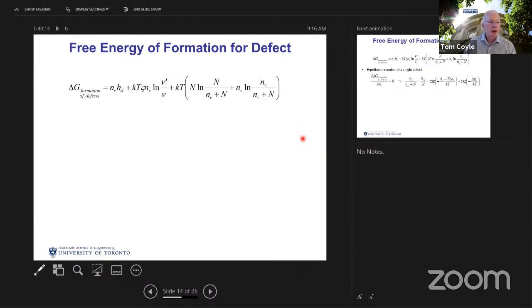Putting it all together, we end up with this expression describing the free energy difference between a lattice containing defects and a lattice without any defects. It depends on the enthalpy of formation of a defect, basically the enthalpy required to break the bonds that hold the atom in that position in the lattice, the number of those defects, the number of nearest neighbors, changes in phonon frequencies associated with the disruption of the bonding, and then this configurational part where we look at the number of defects over the total number of lattice sites.